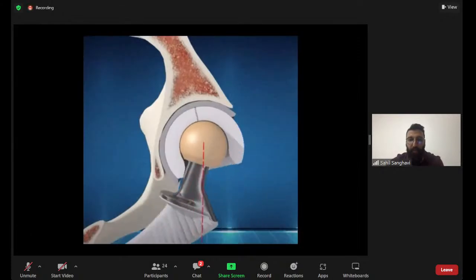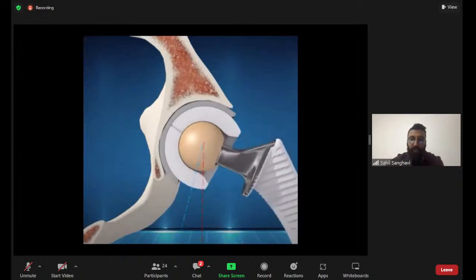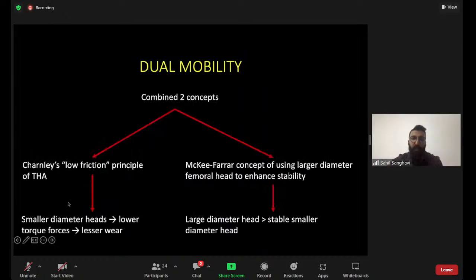So as you can see here, the head will articulate with the polyethylene, and in turn, the polyethylene will articulate with the acetabular shell. So there are 2 points of articulation, which is why it's called dual mobility. So it combines 2 concepts. The first one is Charnley's low friction principle, where a smaller diameter head will give you a lower torque force and produce lesser wear. Whereas on the other hand, it combines the concept of McKee-Farrar of using a large diameter femoral head to enhance stability.